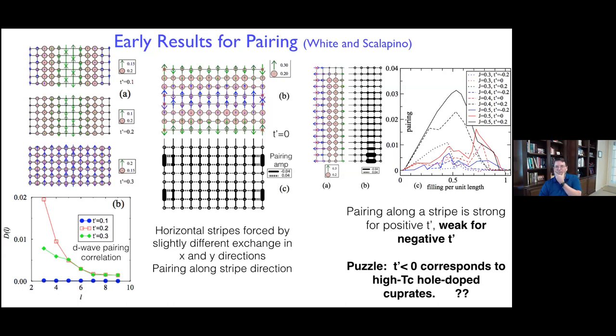Finally, I don't want to give much in the way of details of this right-hand figure, but it shows you the pairing response versus the number of holes per unit length in a stripe. So this is an experiment with just one stripe. The biggest response you get is with this positive T prime. And if you put a negative T prime, you get a very weak response down here.